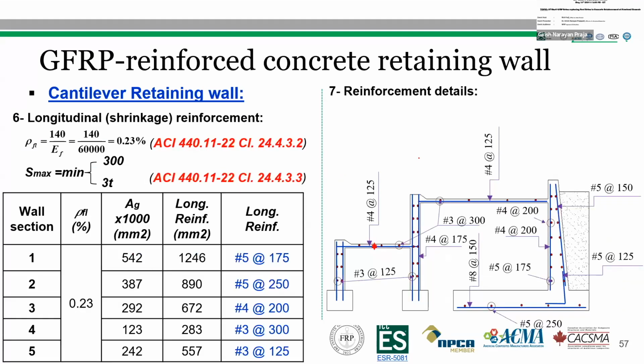So in step 6, we are going to find the longitudinal shrinkage reinforcement. In addition to the main reinforcement with FRP bar, another reinforcement should be provided to control the shrinkage and temperature crack. According to ACI 440.11 clause 24.4.3.2, the shrinkage reinforcement can be calculated using 140 divided by the elastic modulus of the GFRP bar, and this value is equal to 0.23%. The maximum spacing should be limited to the minimum of 300 millimeter or 3 times the thickness of the wall. Based on this criteria, the calculated longitudinal reinforcement is provided in this table, and all the provided GFRP reinforcement details are shown in this drawing.